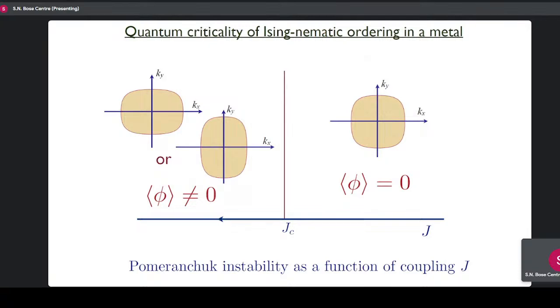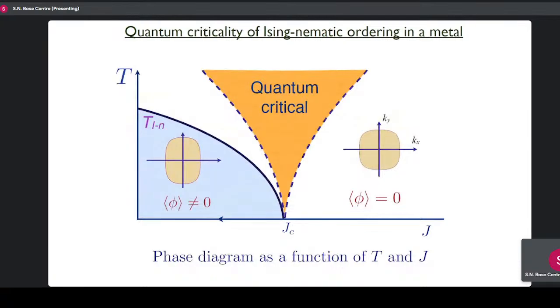Okay, so now there are two possibilities of the square lattice of the distortion, and so you would likely think there's an Ising order parameter, which we call phi, and this Ising order parameter is 0 over here and non-zero in the distorted orthorhombic phase. So now the question is, what happens near this quantum critical point? It's useful to actually think about it at finite temperature. If you add finite temperature, then there'll be a finite temperature phase transition where this Ising symmetry is broken below this phase transition line and unbroken above.